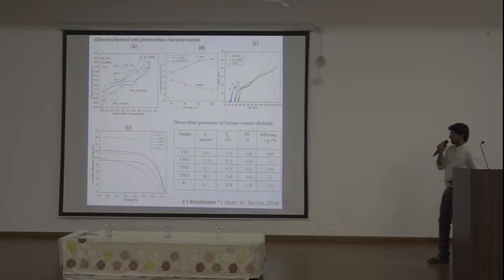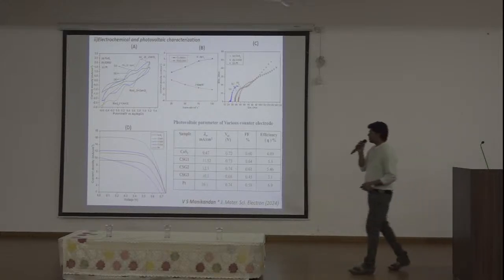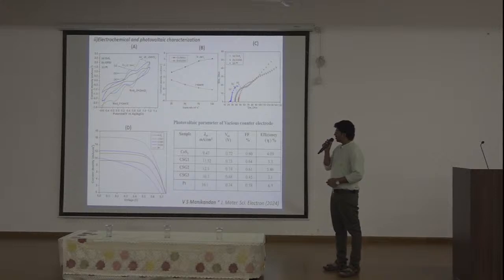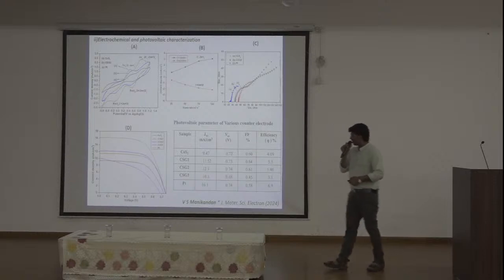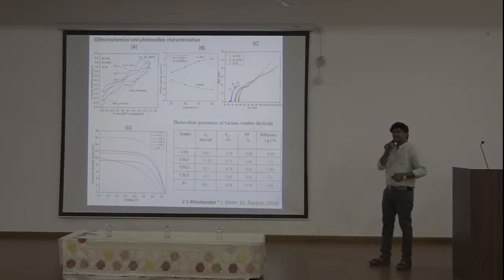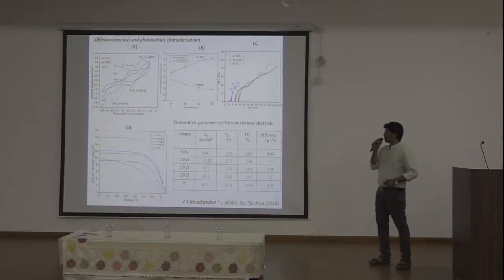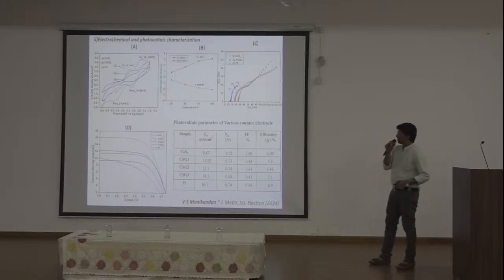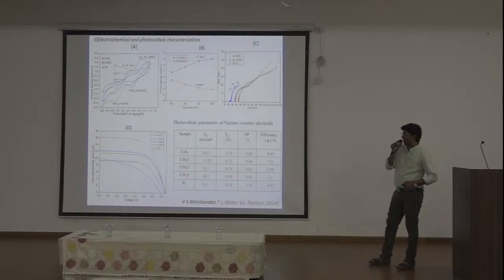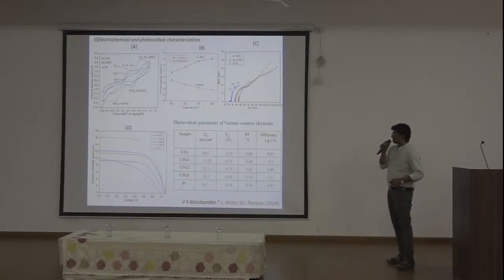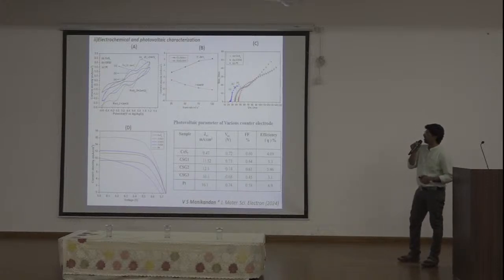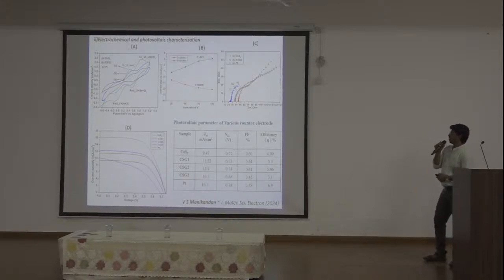So after current and voltage characterization, this is the reference from the platinum-based DSSC device. And moreover, for the cobalt sulfide, even though the short circuit current density is 10, the shunt resistance is increasing. A lower shunt resistance normally indicates a higher leakage path. But in this case, after inclusion of RGO, there is a higher shunt resistance because RGO is providing higher electrical conductivity. This also implies higher current density from the CV plot, and the charge transfer resistance is also decreasing over the frequency region.